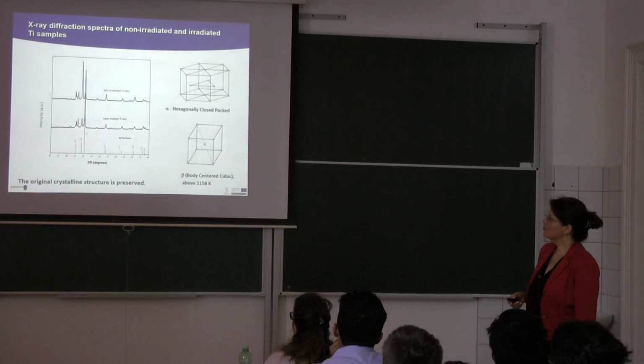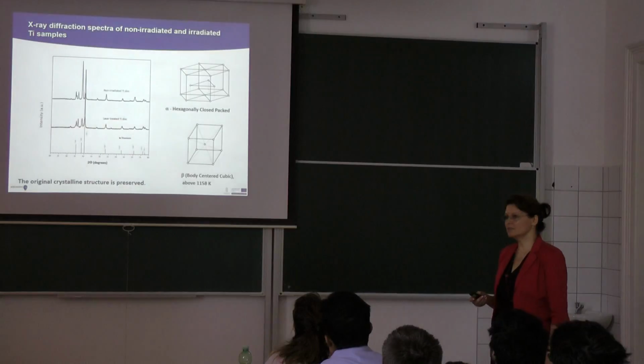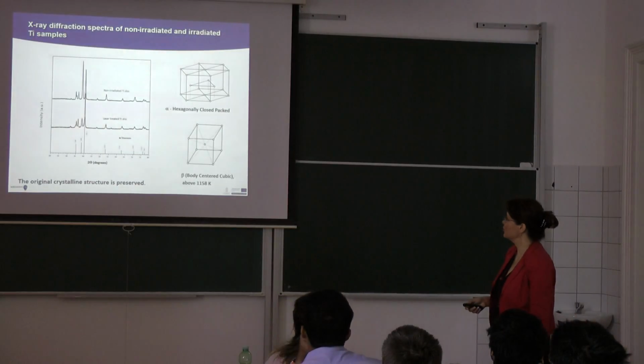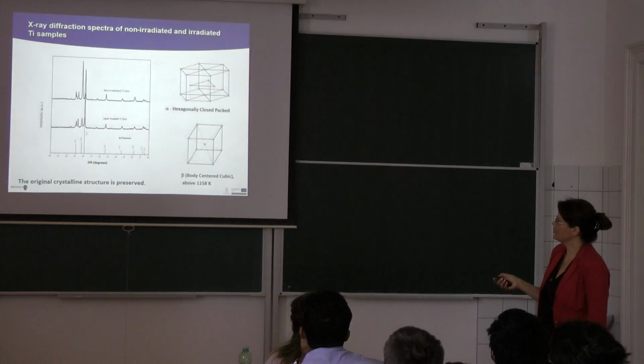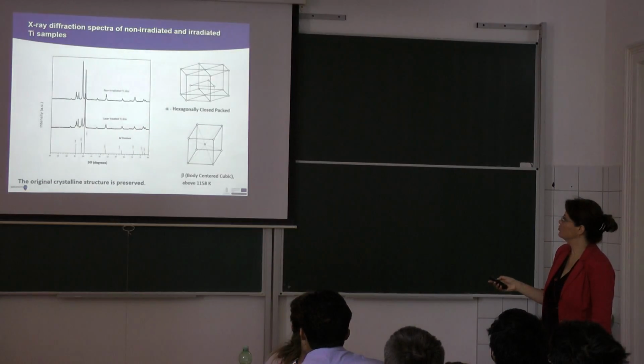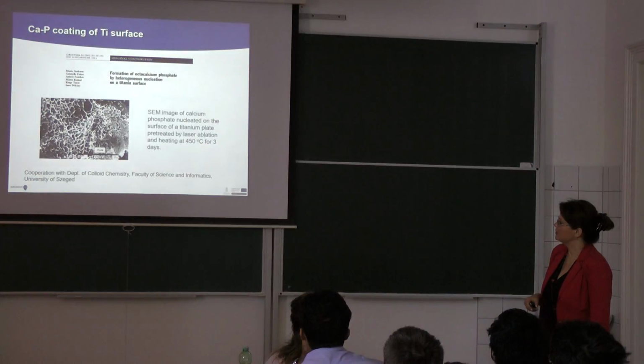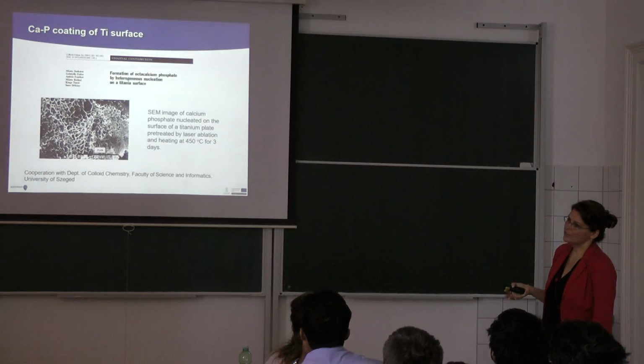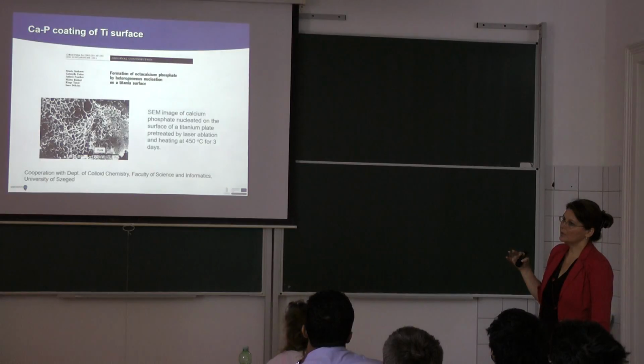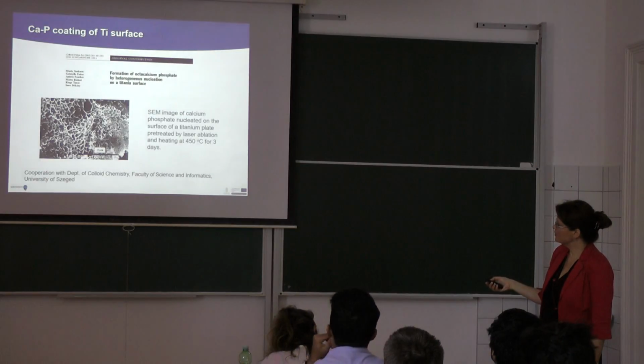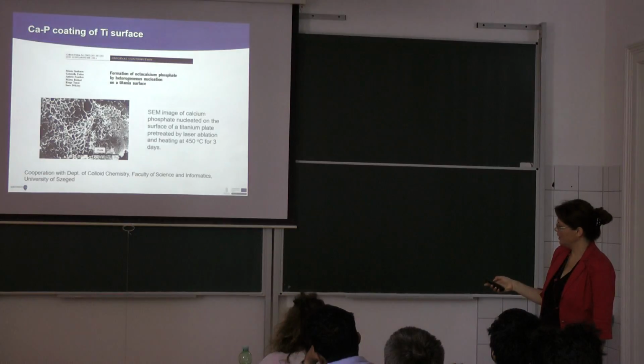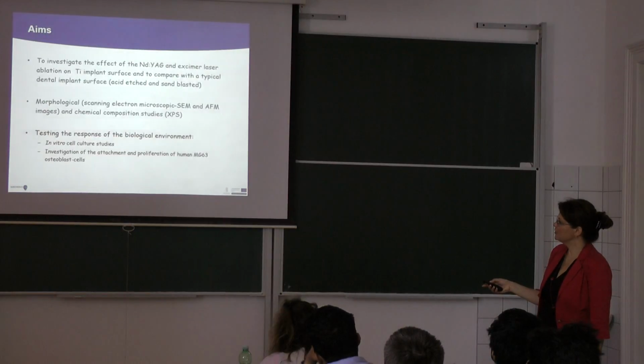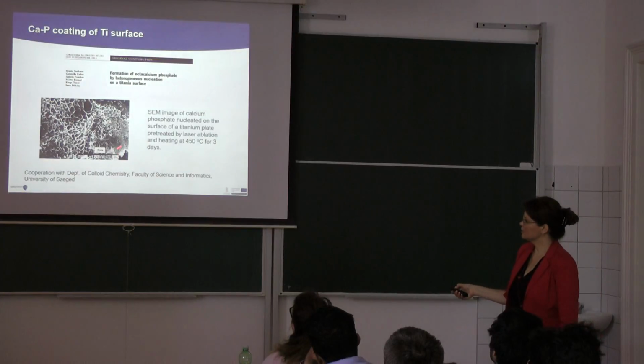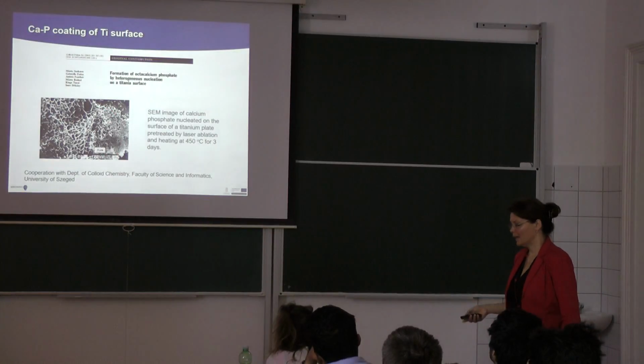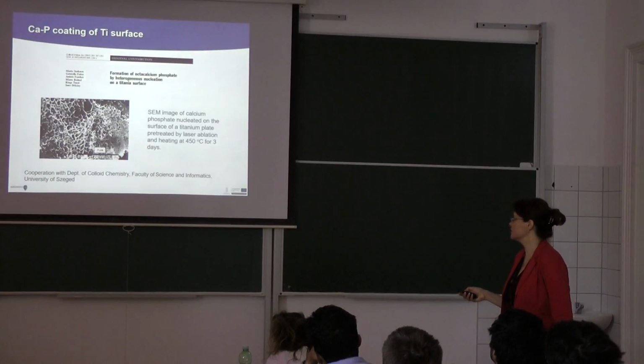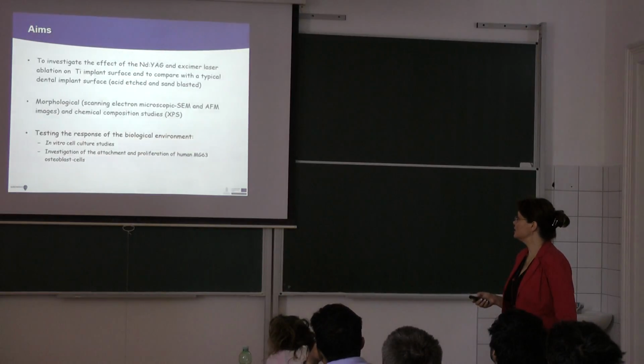Then we also checked the crystalline structure, whether the laser treatment affects the bulk crystalline structure, and we found that no, it was preserved, so it is good and not making anything wrong. Then we applied these laser-treated surfaces by putting a calcium phosphate coating on them. It is a very sophisticated method, by the way, and we found that on the laser-treated surfaces you will have a much nicer coating of calcium phosphate. At that time we wanted very much to test them with in vitro studies, but we could not do it like that.